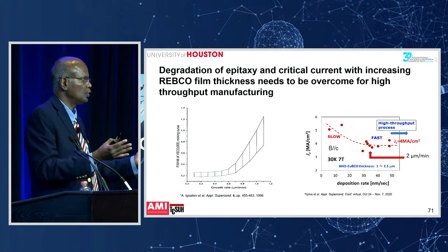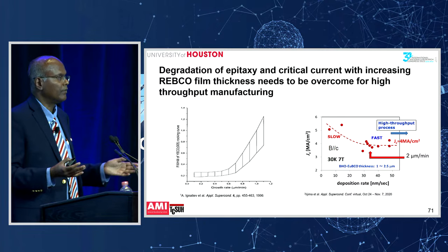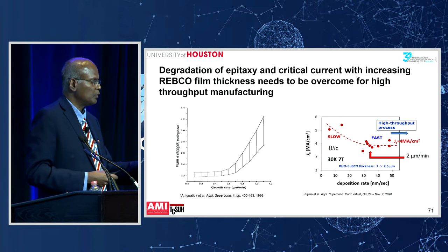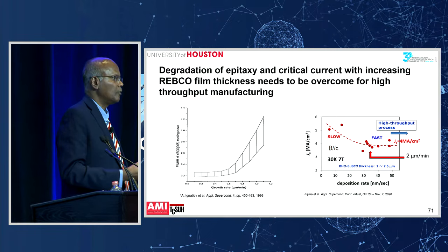Gallium arsenide and gallium nitride and a lot of other films grown by MOCVD and other methods actually degrade when going faster. But we need to come up with a solution. How do you make it go faster? On the right-hand side, I'm showing the current density is actually decreasing as you increase the deposition rate. So those challenges need to be addressed. How do you go faster and still get the same current carrying capacity?